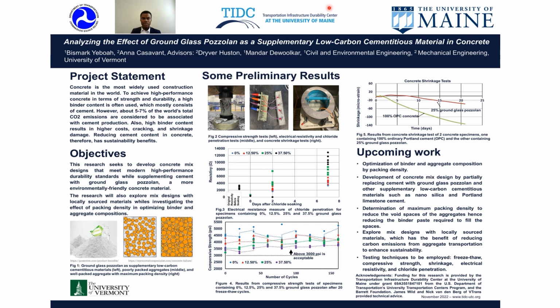Figure 3 shows the results from electrical resistance measure of chloride penetration for specimens containing 0%, 12.5%, 25%, and 37.5% ground glass pozzolan. The original resistivity of the specimens before soaking were all below 4,000 ohms, and the resistivity reduced to less than 1,000 ohms the first day the specimens were soaked. And on the 7th day after soaking, it can be seen here that the specimen containing 37.5% ground glass pozzolan attained the highest electrical resistivity of about 13,000 ohms, followed by the specimen containing 25% ground glass pozzolan.